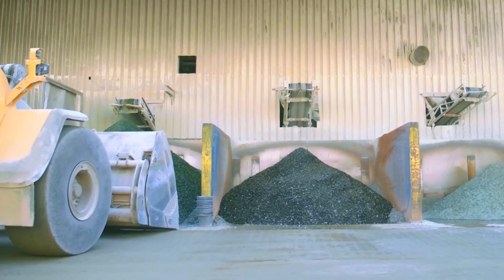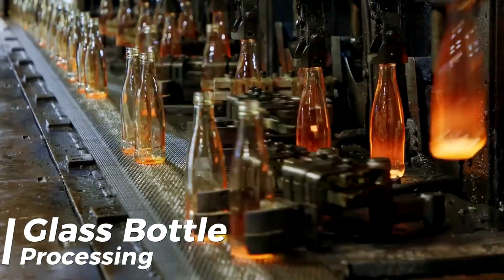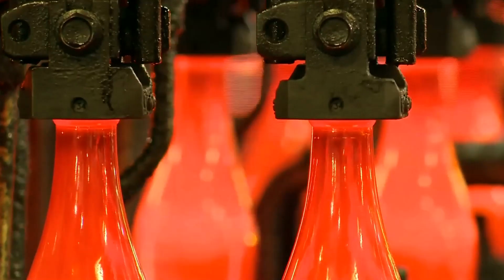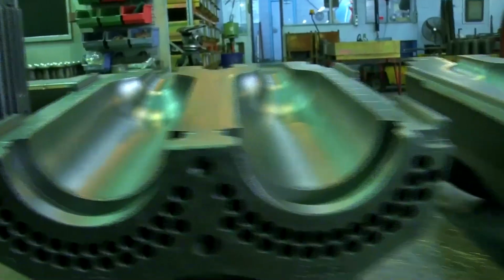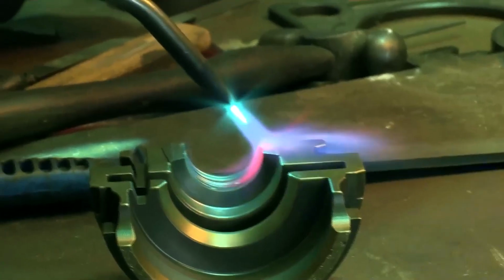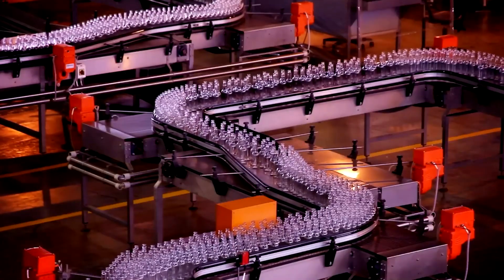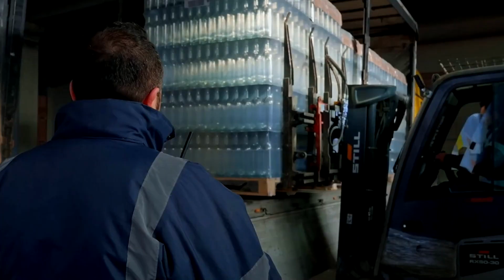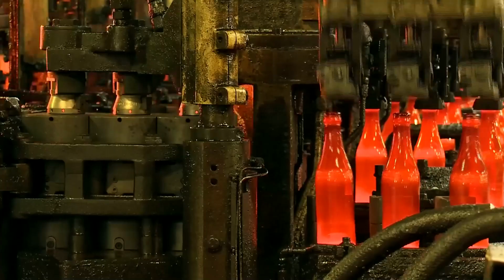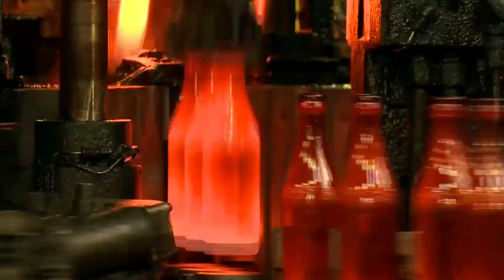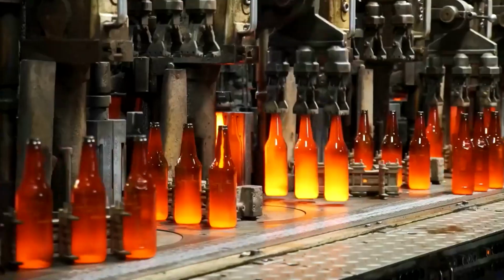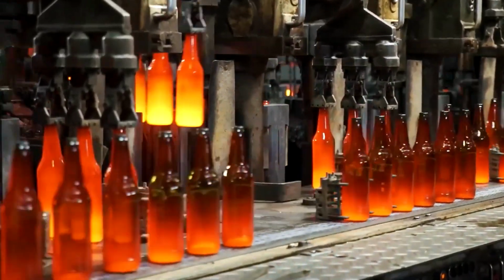Once the molds are fully completed, they are carefully installed into the double blow production line, which remains one of the most reliable methods for shaping hollow products like soft drink bottles and food jars. The forming process initiates by dropping distinct lumps of molten glass, known as gobs, into the initial blank mold. These gobs are severed from a continuous stream of liquid glass, reaching temperatures of around 1,011 degrees Celsius, possessing the perfect viscosity for consistent shaping.